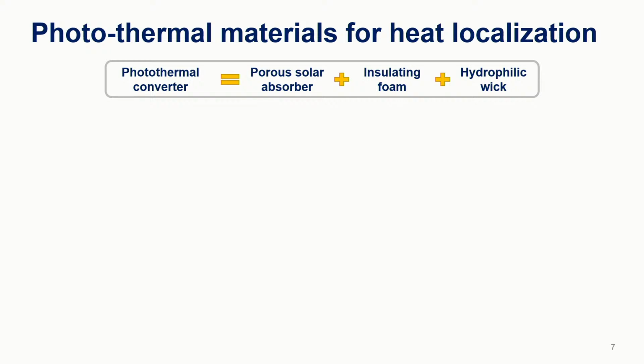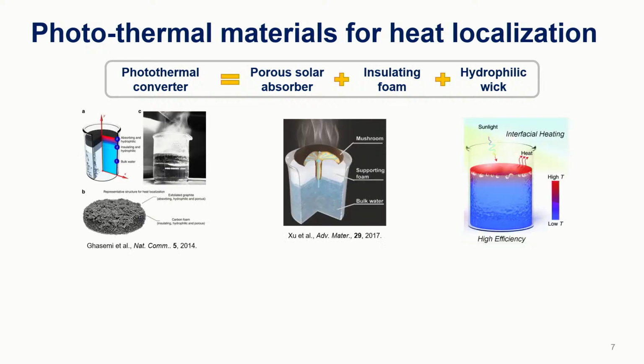So what does a typical photothermal converter look like? It comprises a solar absorber. So this is just a material with a very high solar absorptivity. And then we need some kind of insulating foam-like layer to separate that solar absorber from the bulk liquid, because we want to keep the heat at the surface. And then finally, you have a hydrophilic wick, which is just the material that's now going to deliver water from the bottom to that surface.